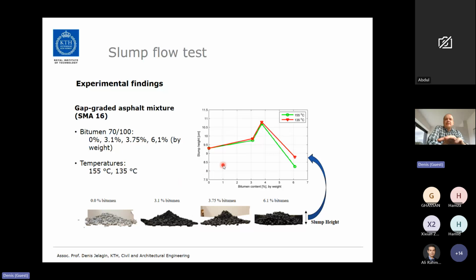And this is how the results look like. So on the vertical axis, we have slump height, and on the horizontal axis, we have bitumen content. And you can see that when we start adding bitumen to unbound material, of course, we provide certain amount of adhesion to the system.